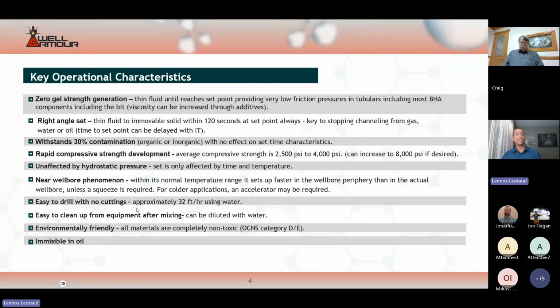It is one set. If you have it in the wellbore and you need to drill it out, it is easy to drill with no cuttings. Average ROP when drilling it out is about 32 feet per hour, but from field observations, we've seen upwards of 40-45 feet per hour ROP when drilling out the Well Armour in the wellbore. It is also easy to clean up from equipment after use. It is environmentally friendly, and it is immiscible in oil because it has a high affinity for itself. So it's not going to want to mix in non-aqueous type fluids.